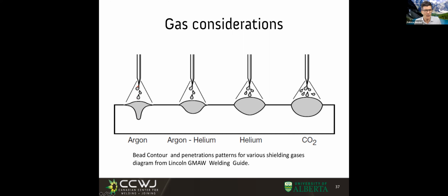This is because argon gives you spray transfer, and the droplets that come actually can penetrate, cutting in, and those droplets dig this distinctive pattern, right? So yes, it's associated with argon, but not because argon has any magic property for penetration. It is because argon has the magic property of giving us the spray transfer that we don't really understand exactly why, but it does. And then the droplets are the ones that have this mechanism.